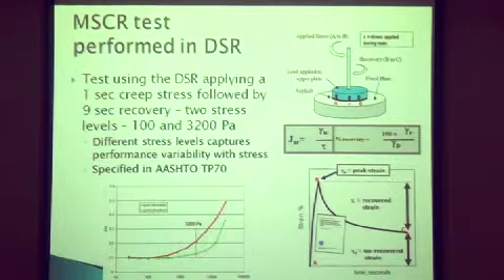So we have this test, MSCR, which is performed in a dynamic shear rheometer. This is showing the test configuration. Here I show you have a sample in a rheometer. Here's a little sample of a binder.